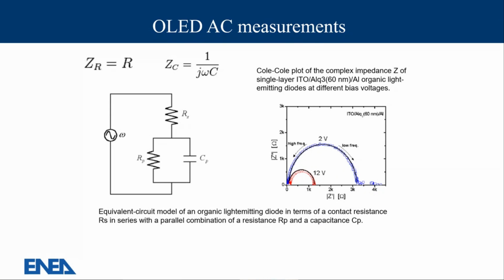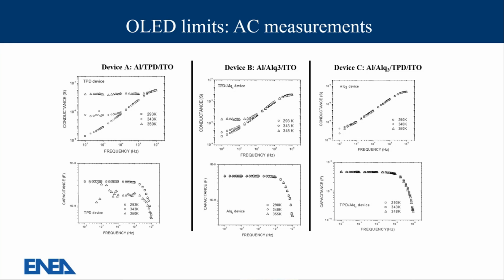Moreover, it's not only the frequency that changes: if we change the bias on our materials, the cycle that we have at higher or lower frequency becomes much smaller, of course, because there is a sort of bias of the charge that passed through the conductive band. So also in this case we can monitor how the conductance changes, changing the frequency and the temperature too, and it was possible to see that we have a region in which there is a mechanism, and another one in which we approach the glass transition.